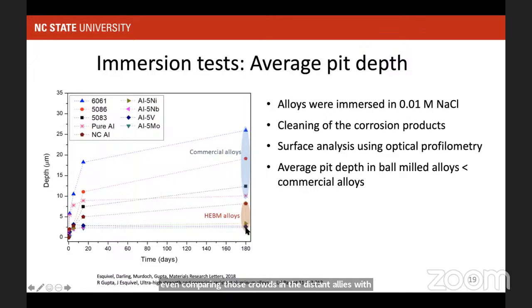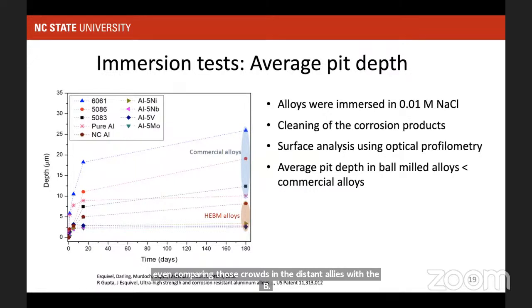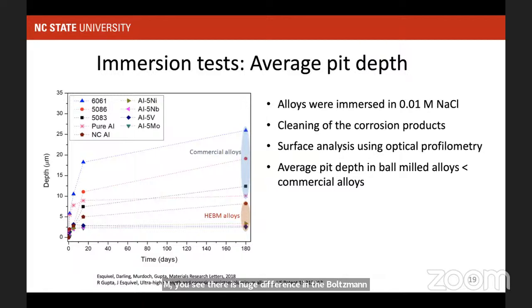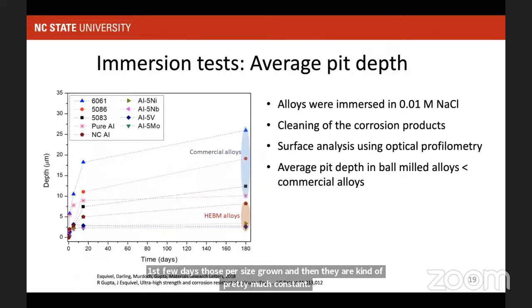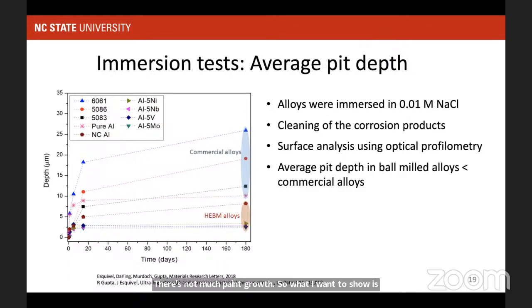In the ball mill materials, the pits form initially, but they don't grow. If I analyze those pits, you see in the first few days those pits have grown, and then they are pretty much constant. There's not much pit growth. So what it shows is these materials are actually corrosion resistant, and it verifies whatever electrochemical data we got.